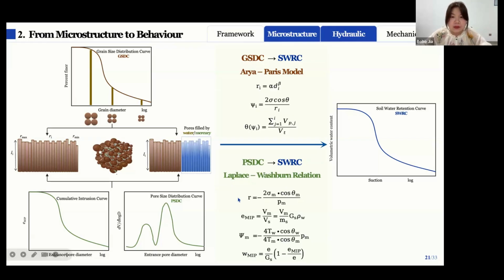And then the Laplace-Washburn relation, which is used together with mercury intrusion porosimetry, because in MIP, mercury is forced into the pores under pressure. Since mercury is a non-wetting fluid, the applied pressure is directly related to the pore size through capillary principles. So by measuring the pressure-intrusion response, we obtain the pore size distribution and then convert it into the suction using the same capillary relationship. In this way, we can also derive the SWRC from the pore size distribution.